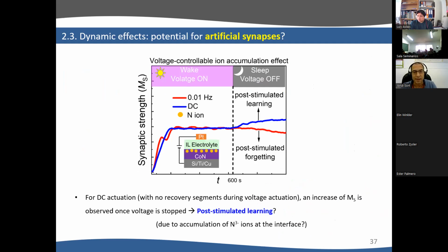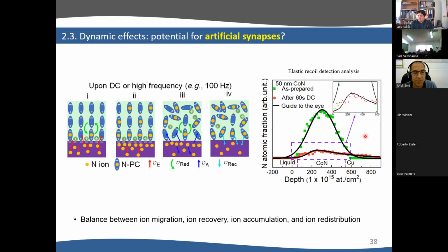Now let's go back to this fancy effect, which is still under review, not yet published. What happens here? Why, if we stop the voltage, in DC, does it continue to increase, but this does not happen at 0.01 hertz? What we think here, and this is just a hypothesis, is that if the layer is very thin, like in this case, you have seen that magneto-ionics is very fast. So the effect is induced in less than 1 second.